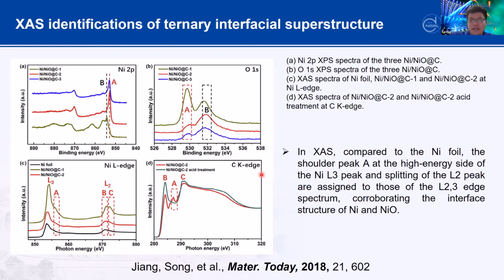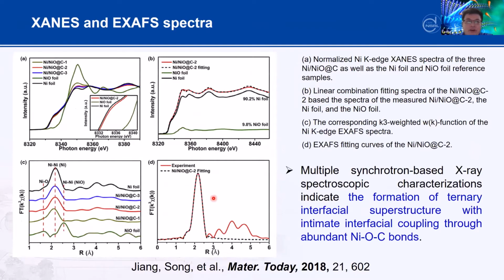This is also the carbon K-edge spectrum. You will see that after the acid treatment, it clearly shows the peak here. This is the additional peak, and by this spectrum we further study XAS, and also XAS on the heavy metal. As you can see in the normalized nickel K-edge XAS spectrum, if you compare the pre-edge, they do show some shifting, but compared to the nickel foil and nickel oxide foil, the valence state is very close to the nickel foil, not too far, which means this is just slightly oxidized. And by the XAS analysis of the R region, you will see by the fitting that it can confirm the formation of the ternary interfacial structure.